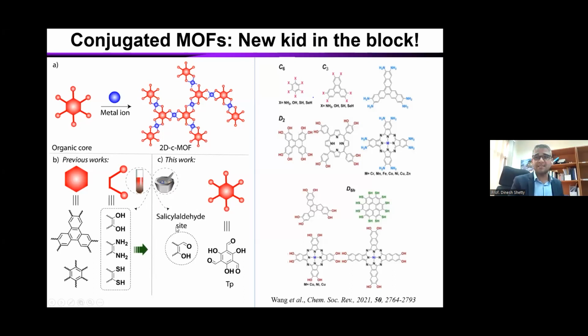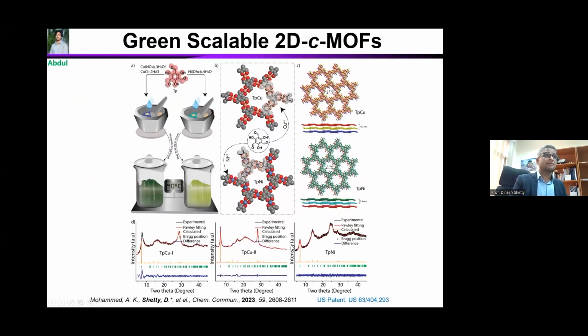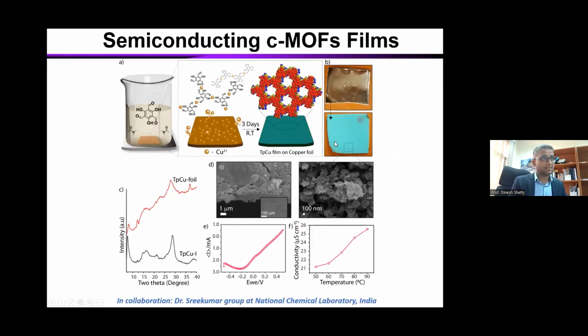This is a much easier, scalable method. Okay? And this is our report. Recently, we reported this method, and now we are scaling it up, and we are using it for many applications. We did this characterization. For example, in this case, we used copper and nickel as metal centers, and the TP as the monomer unit. And it's a very easy mixing. And then thermal treatment leads to the formation of the conjugated system.